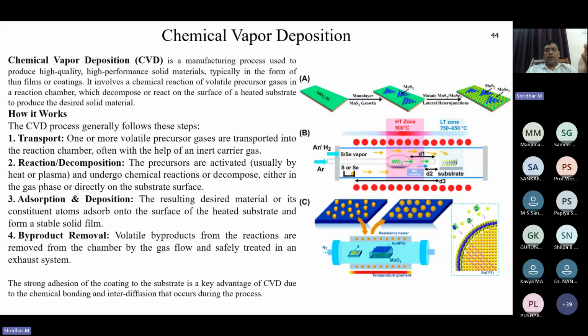And this is also done in a high-end, ultra-high vacuum or else a controlled atmosphere of argon. Okay, this is chemical vapor deposition. What they do, they will be having a precursor already. You can see here, this is the substrate. Silicon oxide is the substrate, and here tungsten oxide is the precursor.